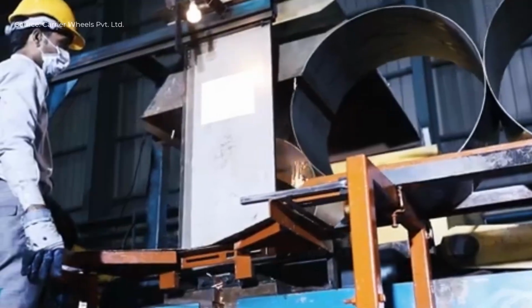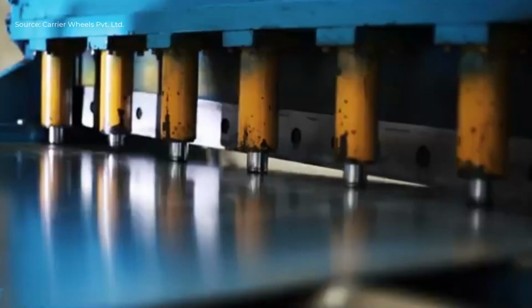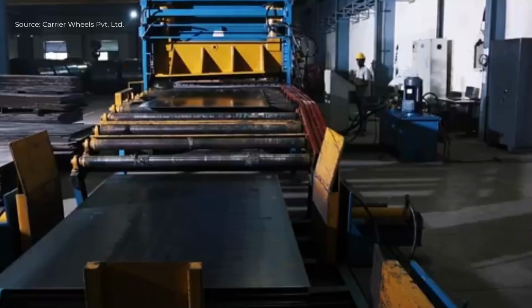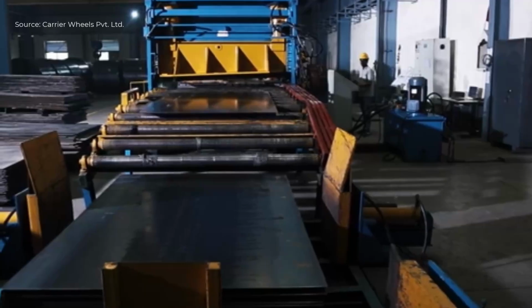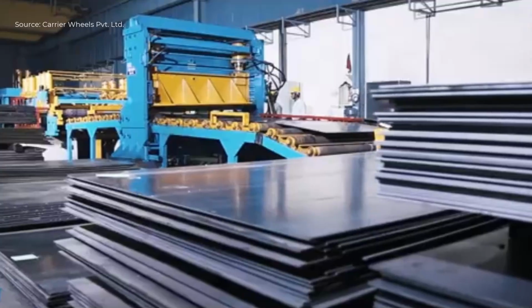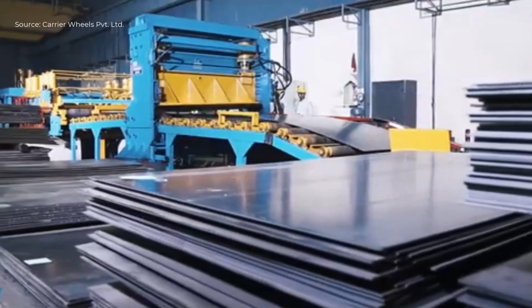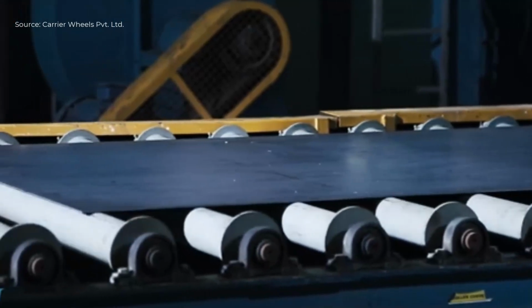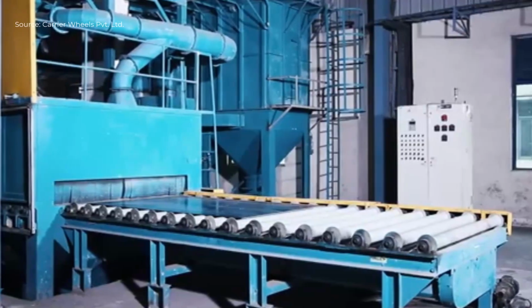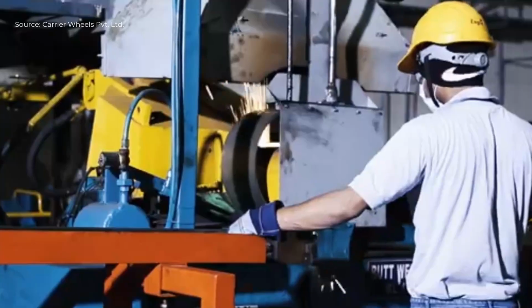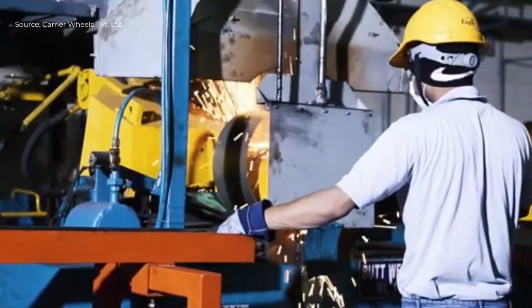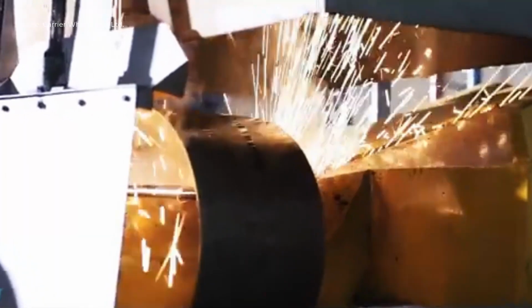The manufacturing process at Carrier Wheels begins with the use of high-tensile and special-grade steel, selected based on application and customer requirements. The steel is decoiled and cut to length before undergoing shot blasting to remove mill scale and induce compressive stress. High-capacity flash butt welders are then used to join the rim components. Roll forming, horizontal flaring, and expanding up to 500 tons shape the rims into final profiles.